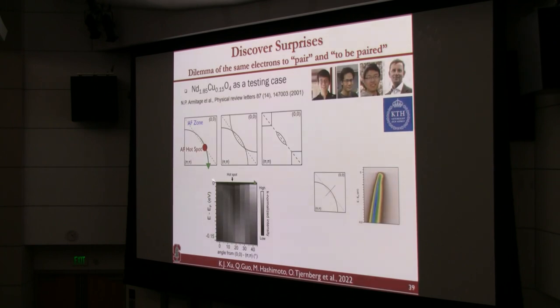And this, again, you have a metal Fermi surface, and the dashed line is the antiferromagnetic zone boundary. If you have symmetry breaking, you have band folding, and you open up a gap at the boundary. What in the field you call the hotspot. Now let me show that if I take spectra across this at a larger scale, in this grayscale, you can see that as I go from the node towards the other side, going through the hotspot, you see a large region of spectral weight suppression. Now I'm going to show you a movie of cutting around here, and you can see here.